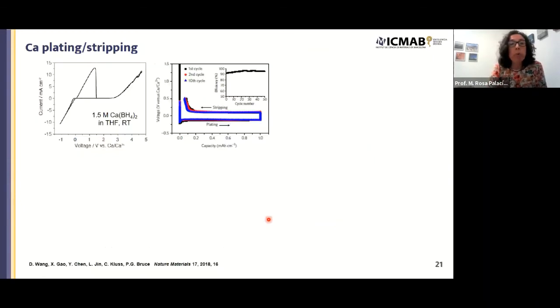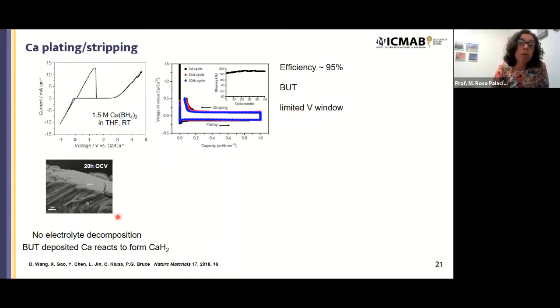After we reported those results, other electrolytes have been suggested to be viable for calcium batteries. This is the first, by the group of Peter Bruce. In this case, they are able to plate calcium at room temperature using this electrolyte in a tetrahydrofuran solvent. The main issue here is that the stability of this electrolyte upon oxidation is not very high, so you will not be able to use cathodes operating beyond maybe 2.5 volts, but the efficiency is rather good. One issue is that as soon as it is deposited, calcium starts to react with this electrolyte and also forms a calcium hydride layer.